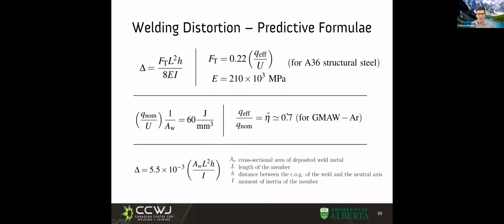So if we say for MIG it is more or less 0.7 thermal efficiency, we combine all this together, right? This nominal times efficiency would give us the effective value, and times 0.22 gives us the tendon force. And if we combine all this, we get this formula, which we have done from first principles. We didn't invent anything, and it says that the deflection is this coefficient of 5.5 times 10 to the minus 3 times the cross section of the weld, length of the beam, distance to the neutral axis, over the moment of inertia.